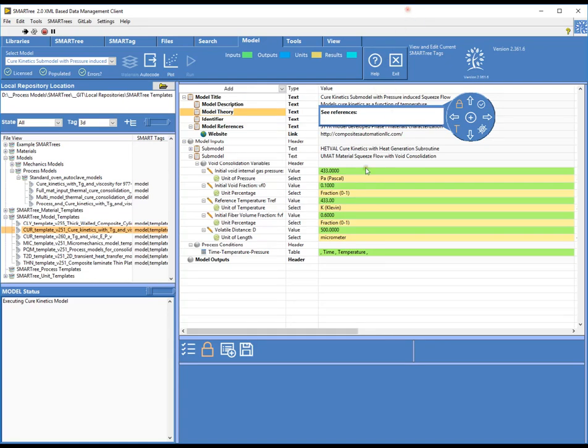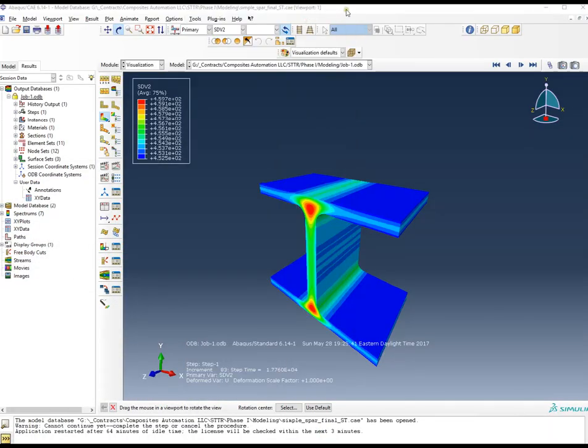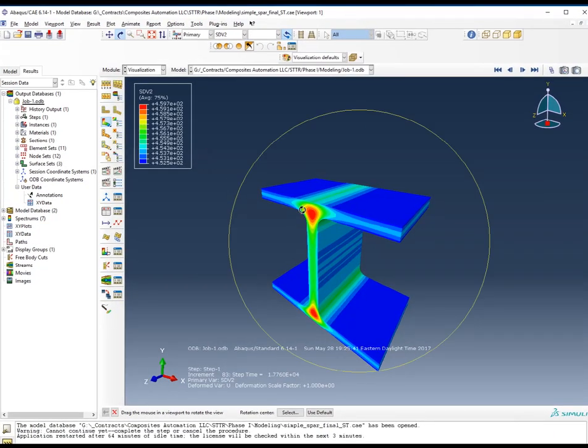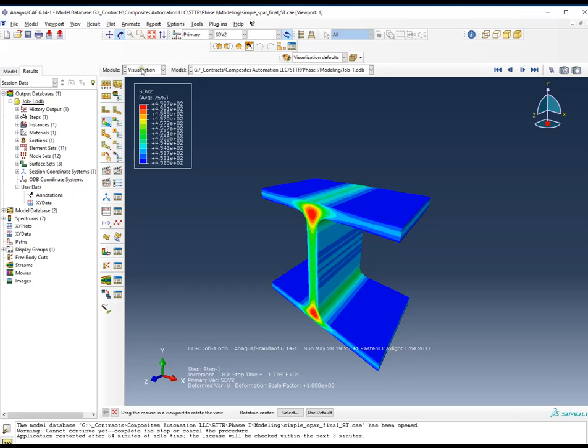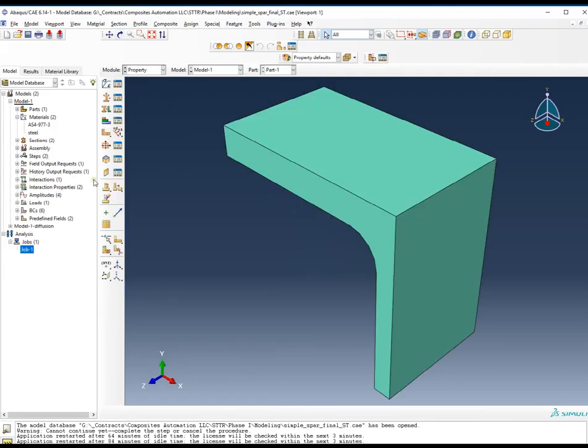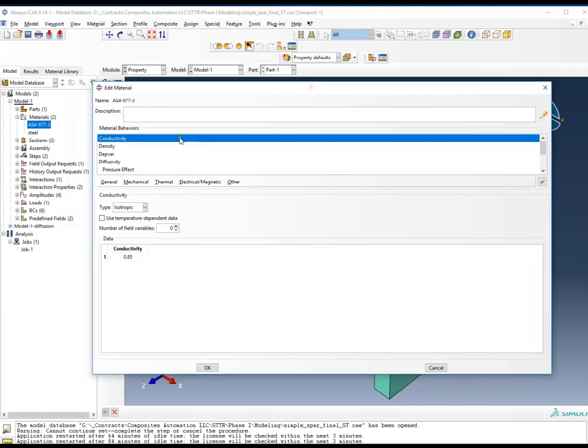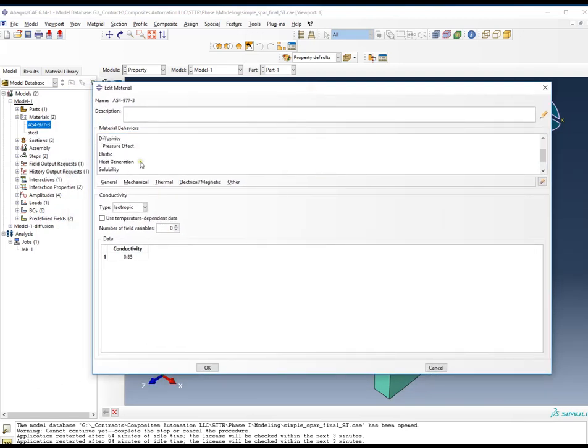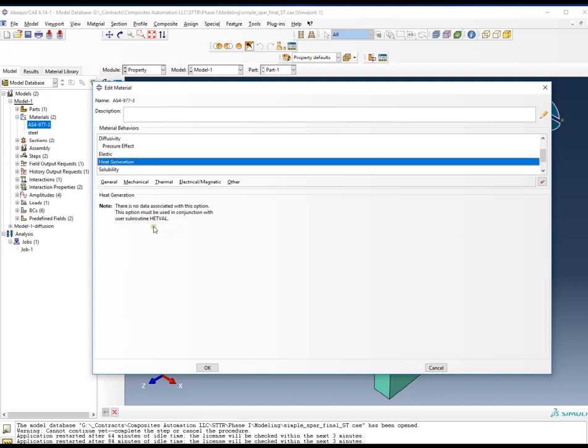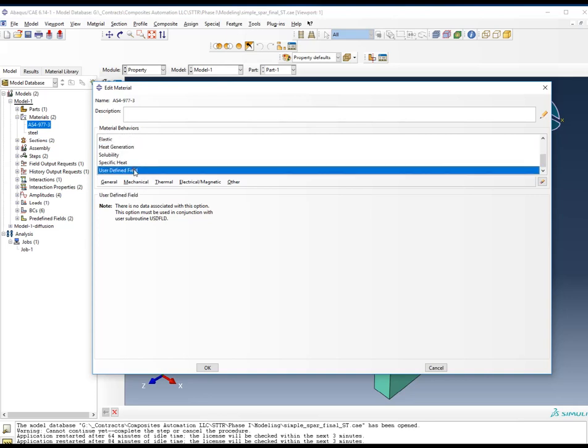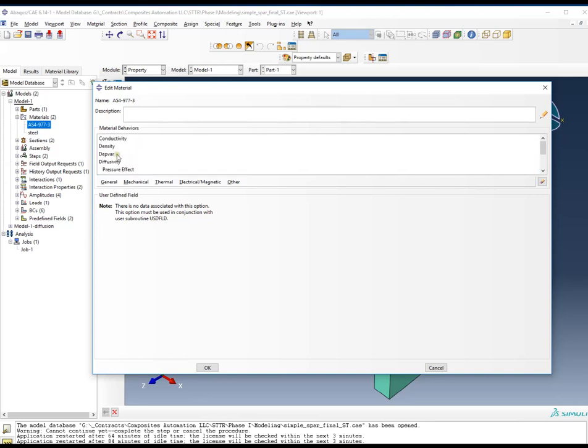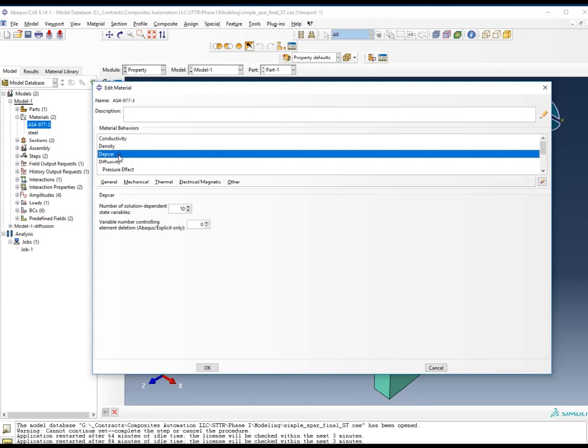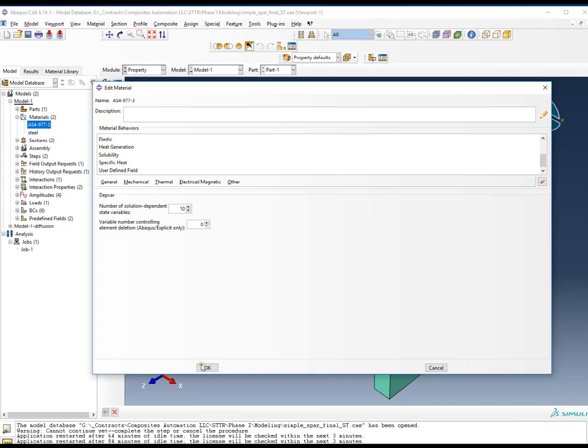So if I want to invoke these values in an abaqus routine, that's pretty straightforward. So here I have a pre-built SPAR model. And what the steps required to run that are as follows. So if I go into the input deck, there is basically just a couple of steps here to be able to pull and run that abacus subroutine. The first is you need to go into your material and you need to activate a couple of material submodel attributes here. One of which is heat generation because that involves the HETVAL routine, the routine we just generated. The other is to be able to define the solution dependent variables. In this subroutine that we generated here, there are 10 solution variables. So we just need to make sure that this number here is 10. And that's really all you have to do in the material window.